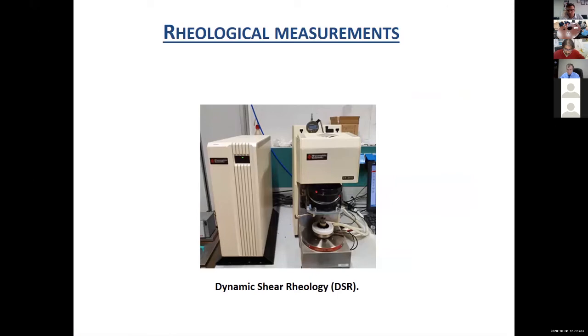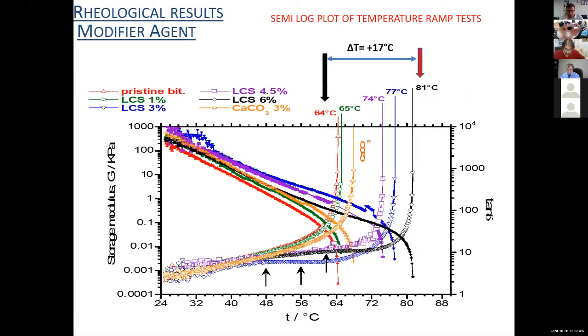To determine the transition temperature, rheological measurements have been done. In particular, the dynamic temperature ramp test from 25 degrees up to 100 degrees at a rate of 1 degree per minute at a frequency of 1 Hz was performed on all samples. In this picture, we show a semi-log plot of temperature ramp tests for the pristine and modified bitumens formulated with 1 to 6% of the additive. The effect of inert filler, calcium carbonate, was also determined for evaluation of the effectiveness of the additive on the bitumen.